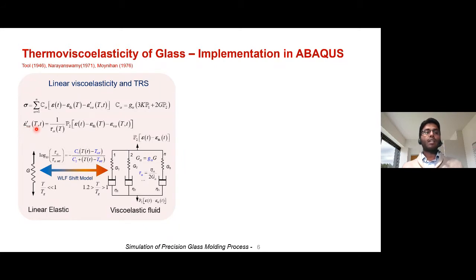Here I'm considering that the deviatoric part of the viscous strain tensor is participating in relaxation. In other words, the flow behavior is happening due to the deviatoric component. That is why you have a dash over here, and this is the relation we use. Once you substitute the sigma over here and do a little readjustment, you can express it in terms of stress relaxation time.